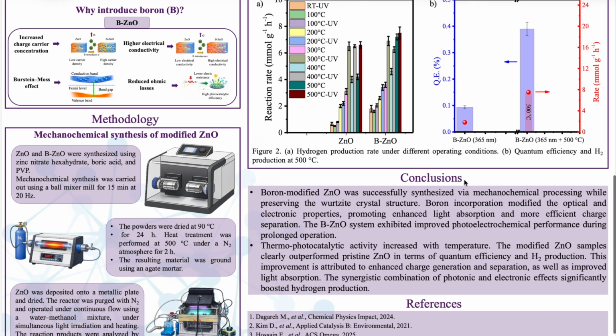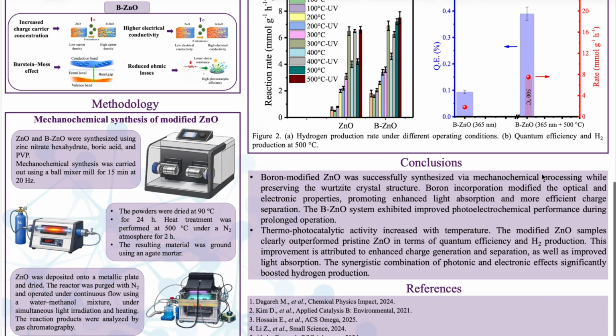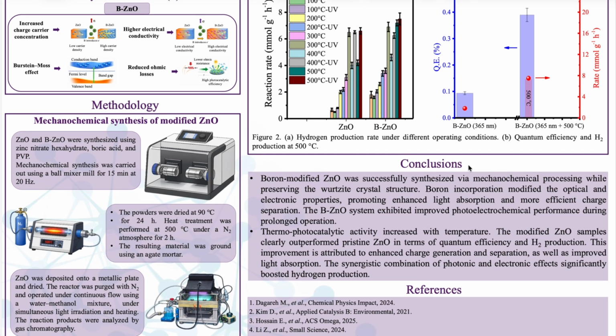Conclusions. In conclusion, boron-modified ZnO was successfully synthesized via mechanochemical processing while preserving the Wurtzite crystal structure. Boron incorporation modified the optical and electronic properties of ZnO, promoting enhanced light absorption and more efficient charge separation. The BZnO system also exhibited improved photoelectrochemical performance during prolonged operation. Furthermore, thermophotocatalytic activity increased with temperature. The modified ZnO samples clearly outperformed pristine ZnO in terms of quantum efficiency and hydrogen production. This improvement is attributed to enhanced charge generation and separation, together with improved light absorption. Overall, the synergistic combination of photonic and electronic effects significantly boosted hydrogen production.